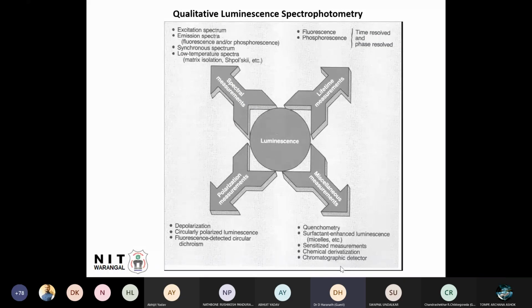you can use them for the photoluminescence technique. And with the photoluminescence technique, using a spectrometer, you can record the excitation spectrum and emission spectrum, in both fluorescence mode and phosphorescence mode, synchronous spectrum, low temperature spectrum, and many other things. Similarly, lifetime measurements: how much time the electron is sitting in the conduction band. Fluorescence, I told you, is 10 power minus 8 seconds, and phosphorescence is more than 10 power minus 5 seconds, sometimes even hours, days, I told you.